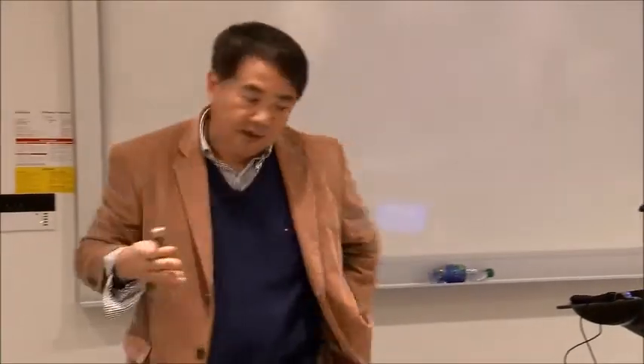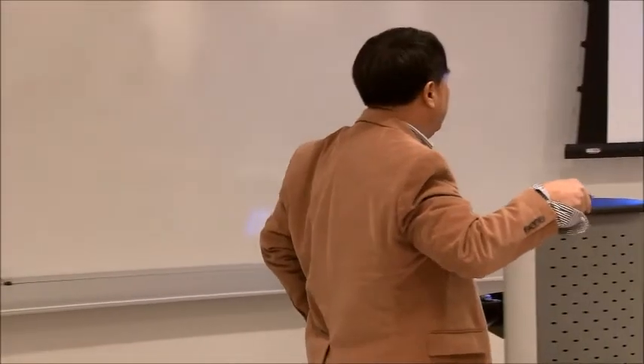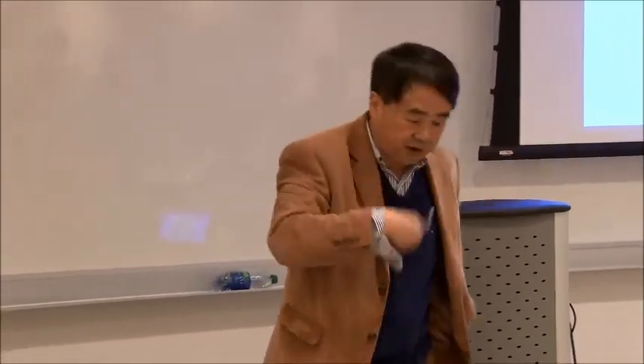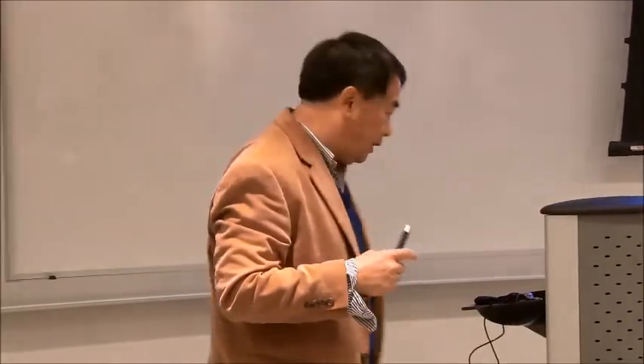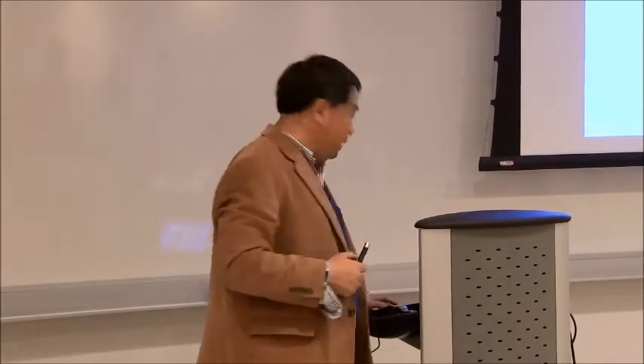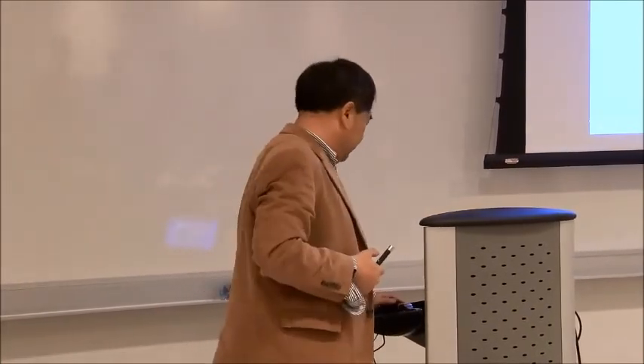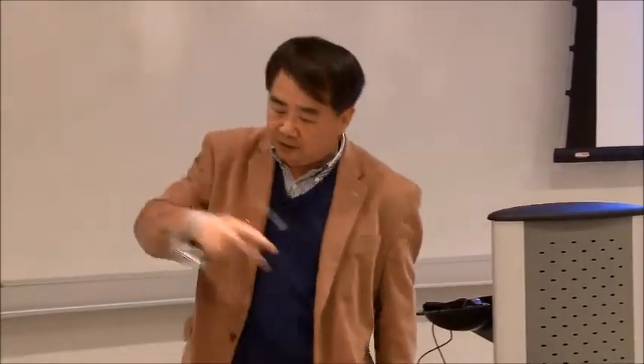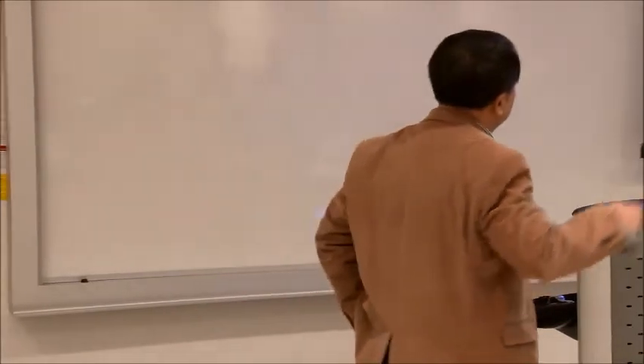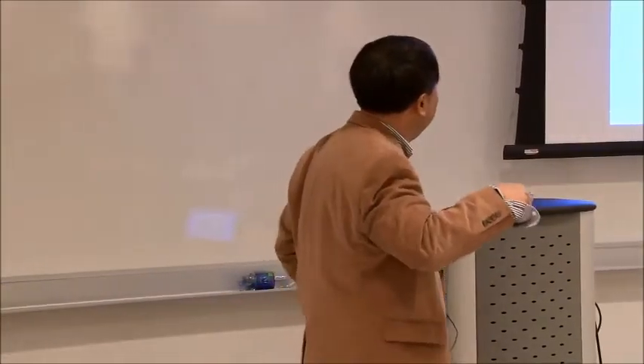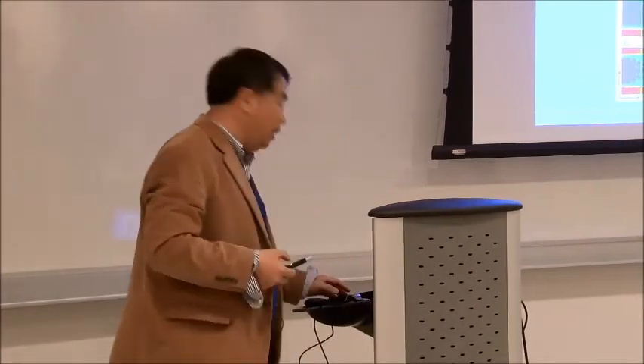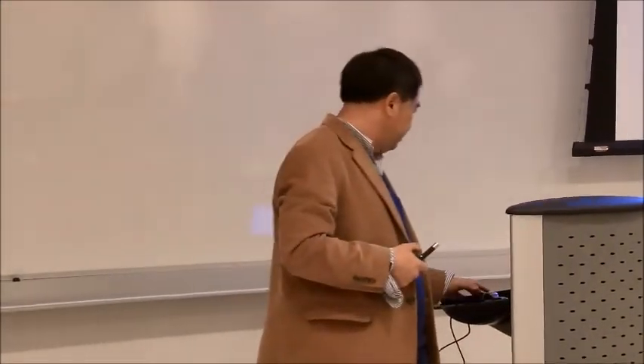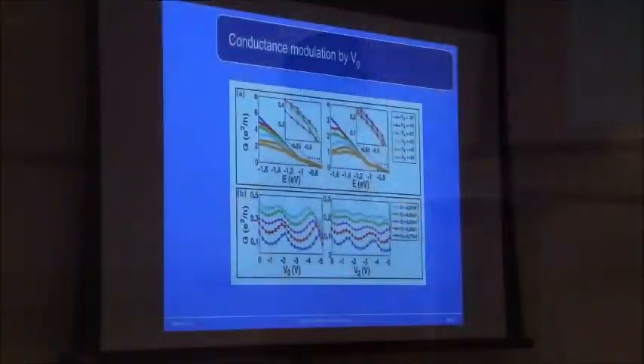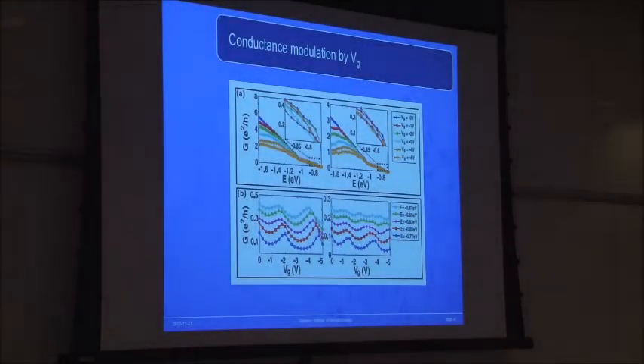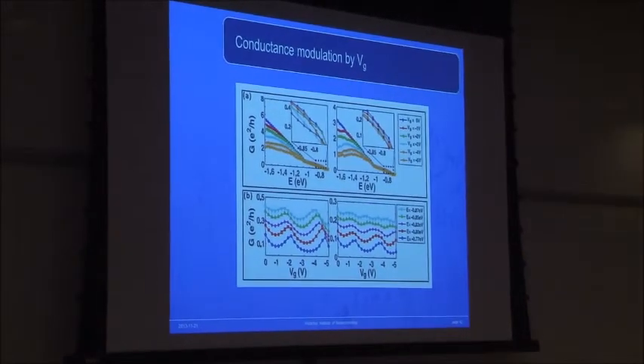So you can actually calculate this spin texture and whether it's 90 degrees or not 90 degrees. So you can see that this spin texture is really changing due to the external field. So we succeeded in changing the spin using an electric field. That is something that the spintronics people like to have. Okay. So there are many other methods which do this, but it seems that in this material you can easily do this with a few, actually 5 volts of voltage. You already see it. I mean, even 1 volt you can already see it. So this seems to be a very large effect due to the large spin orbital coupling. And then your conductance will be modulated by gate voltage due to this spin precession, actually. So that is the physics that this material can give us.